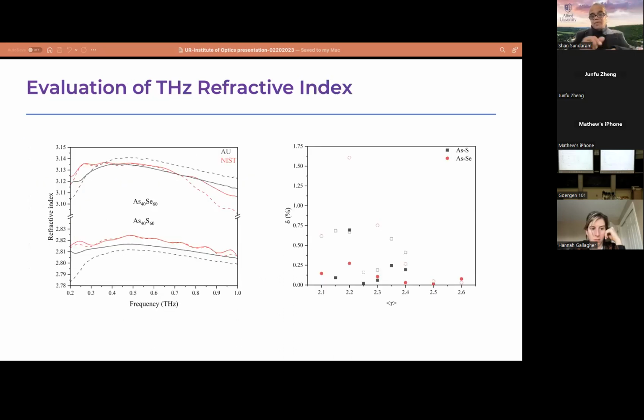The first slide I want to show you is to let you know we did compare our data set with the NIST data set. I'm showing you 2 different data sets for arsenic selenide and arsenic sulfide. The red curves are what we collected at NIST, and the black curves are collected at AU. And the delta is we compared at various frequencies or selected frequencies for all these compositions. How much is the variation of the value we are finally measuring in these 2 different instruments?